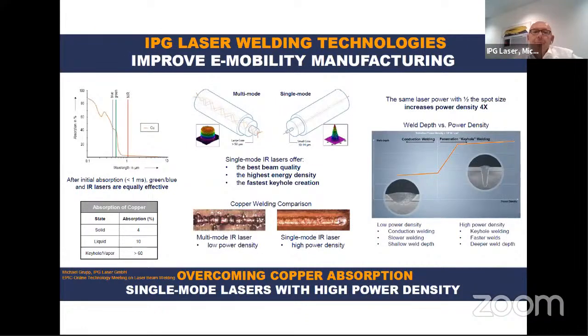So I already said we have to overcome this low absorption, and this is done by means of the high power density. When we look at the left side, we see this table where, in solid state, we have just 4% of absorption for the infrared laser wavelength. But as soon as we overcome this solid state, we come to the liquid state, to the keyhole, and suddenly get to 60% and more of absorption of the infrared. And this is not much less than for other wavelengths like green or blue.